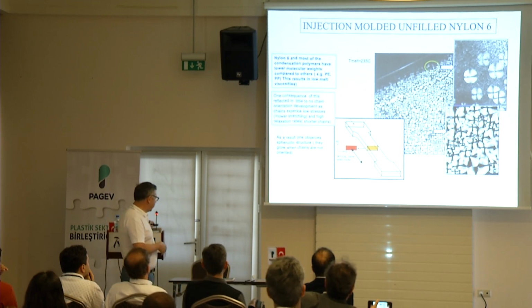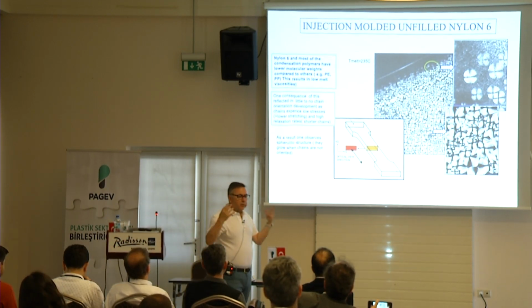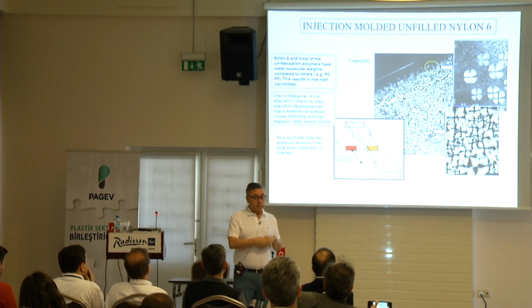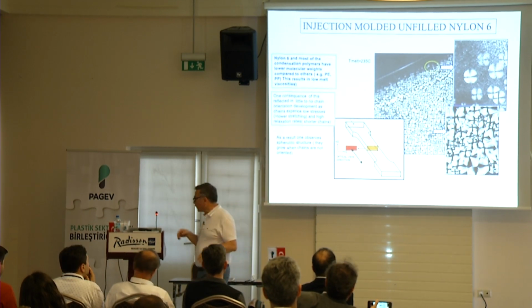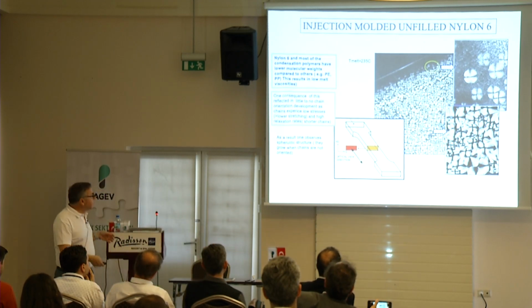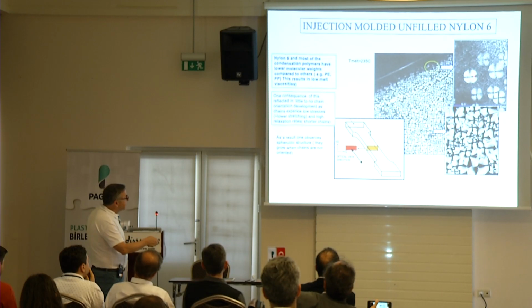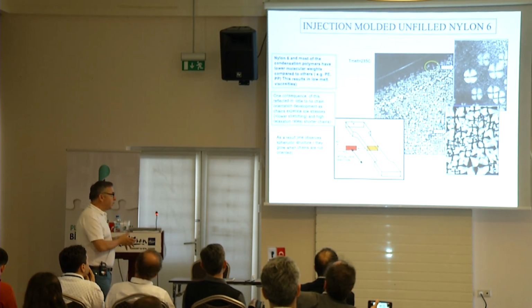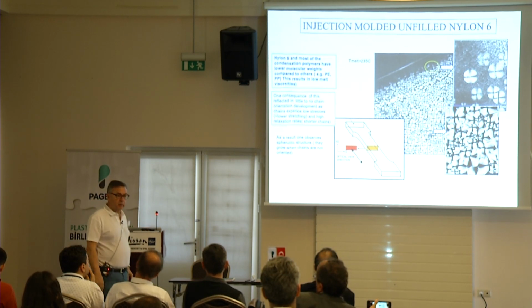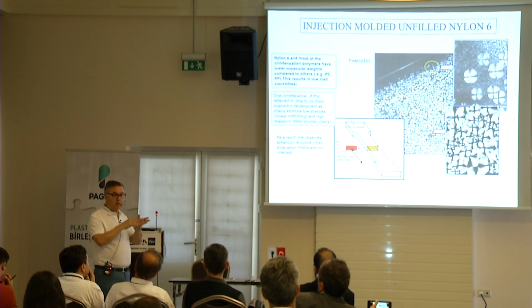It doesn't show a very dramatic shear-oriented layer. The reason is nylons have very low viscosity, right? If they are polycondensates, they have very low viscosity. So all you get is thermal crystallization, except maybe near the skin. If you look at it, it's a spherulite just frozen in space. And you have larger crystals and smaller crystals closer to the skin. So no matter what you do, nylons do not orient because you don't have this mechanism of shearing, because the viscosity is so low that the material just simply doesn't shear very well. You cannot transmit forces to local polymer chains. It's classic.